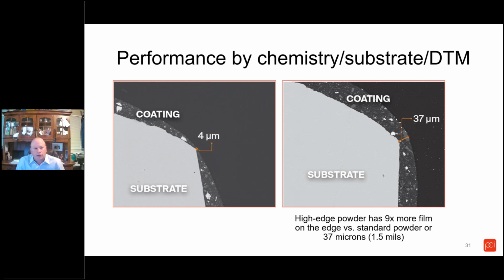So if you look at the cross section on the screen on the left, it's just a standard coating, and you're able to build about 4 microns, or a little less than 0.2 mil. But with products engineered specifically for edge coverage, we can improve that by about 9 times, up to 37 microns, or about 1.5 mil. So obviously, in a highly corrosive environment, the product on the right side will perform better.